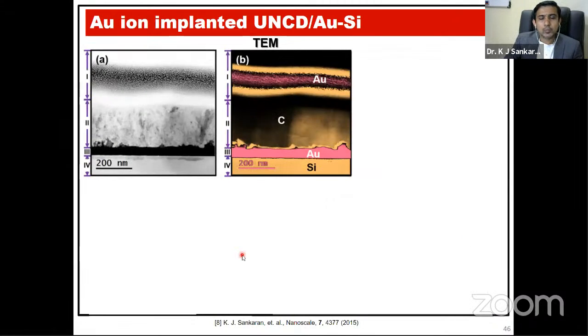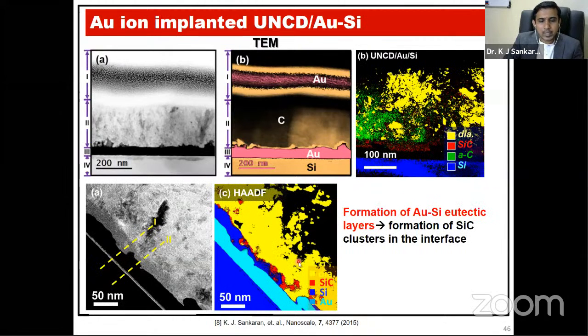Also, we carried out further studies with TEM, EDAX, as well as some HAADF images, which confirm the presence of carbon. So silicon carbide forms between the gold and the UNCD films, and the colored images from the TEM also represent the presence of silicon carbide in the interface between the gold and the UNCD.